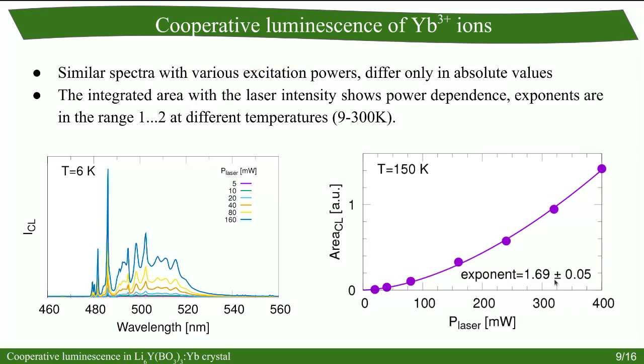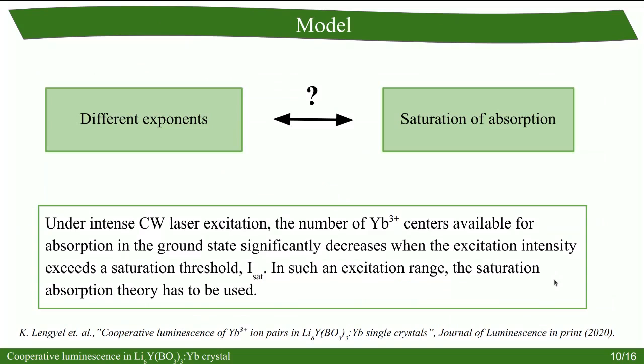So we recognize that in different temperatures we have exponent values from 1 up to 2 when the temperature changes from 6 up to 300 Kelvin. So after these measurement results, we think about the reason of this interesting effect, and we have an idea that maybe the saturation of the absorption somehow can relate to the different exponents.